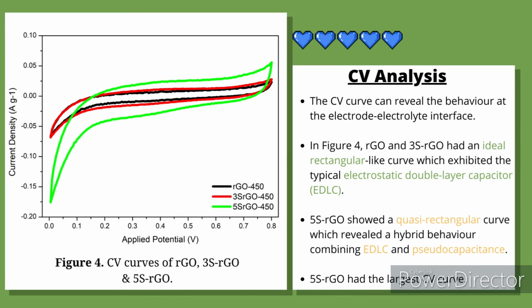And finally, we have the cyclic voltammetry analysis. The CV curve can reveal the behavior at the electrode-electrolyte interface. In Figure 4, RGO and 3S-RGO had an ideal rectangular-like curve which exhibited the typical electrostatic double-layer capacitor or EDLC. For 5S-RGO on the other hand, it showed a quasi-rectangular curve which revealed a hybrid behavior combining EDLC and pseudocapacitor. 5S-RGO had the larger CV curve.